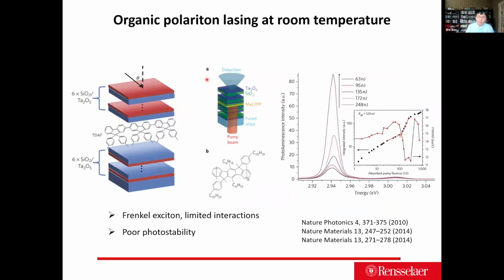And the other room temperature effort goes into organic polaritons, and as early as the Nature Photonics paper demonstrated by Stephen Forrest and Stéphane Kéna-Cohen back in 2010, essentially you can embed a lot of this organic material into the dielectric cavity structure and demonstrate polariton lasing even up to room temperature. However, as we all know, this organic material tends to have excitons that are very localized to a certain molecule. That's a good and a bad.